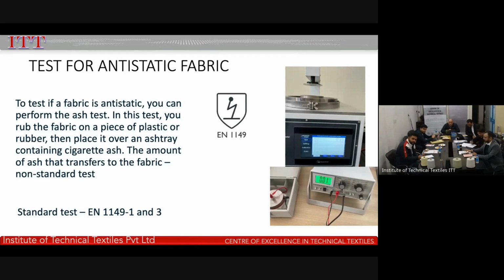Now, one of the general fears is, how do I test whether my fabric has the antistatic fiber or not? The simple way is just to rub the fabric on a piece of plastic or a rubber. If it generates a static charge, it will pick up some ash from the ashtray, and that means it does not have the antistatic yarn in it. If it does not pick it up, well, it has the antistatic yarn in it, because it is very difficult for a layman to really test the fabric whether an adequate amount of antistatic yarn has been added or not.